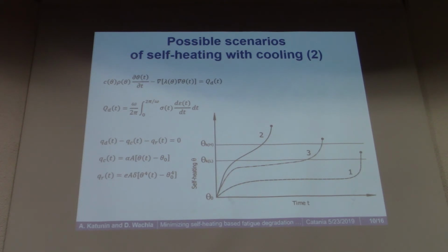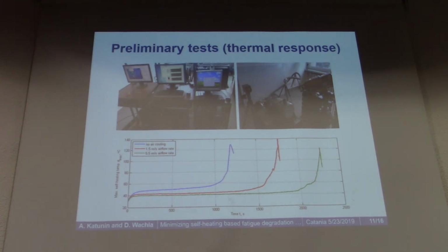And we did some preliminary tests of fatigue loading of composite structures that are subjected to self-heating with air cooling. Here you can see the experimental facility. We did measurements of temperature, of loading, controlling the loading, also acoustic emission, and you can see here the installation which allows us to blow air onto our specimen. On the chart below, you can see three cases we tested: the case with no cooling, and two cases with cooling at different cooling speeds.